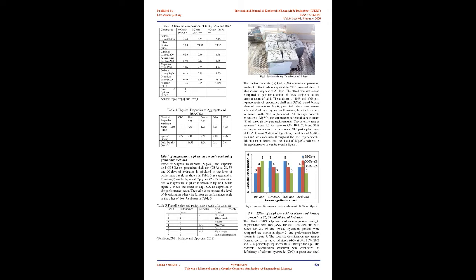Although BSA possesses similar chemical composition to GSA, it has a low content of SiO2 of 33.36% as compared to GSA and Portland cement, and therefore does not satisfy the pozzolanic requirement.